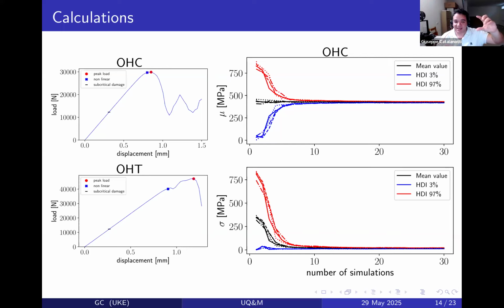But as soon as I run a few simulations, after 20 simulations, those hyperparameters have converged, and they don't move anymore. You can run even 2000 simulations. You have frozen the hyperparameter. Same thing for the standard deviation. A large standard deviation at the beginning, of course, this has to be just positive, and little by little, this standard deviation goes to zero.